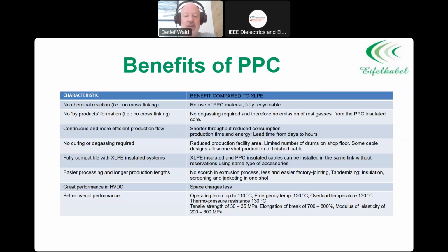Tandemizing, for medium voltage at least, you can make the insulation, which means the cable core, the screening and the jacketing in one shot. The space charges for HVDC in polypropylene are lower, and I will come back to that later. The thermal performance: the operating temperature can go up to 110 degrees. Emergency temperature, like XLPE, up to 130. Overload temperature also in that area, and you still have very good mechanical properties.